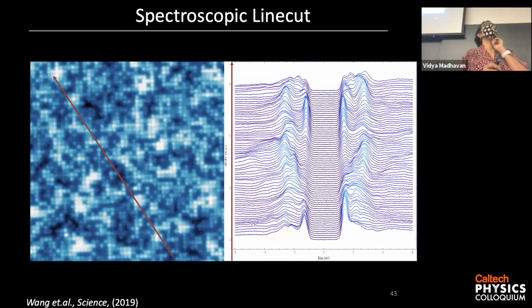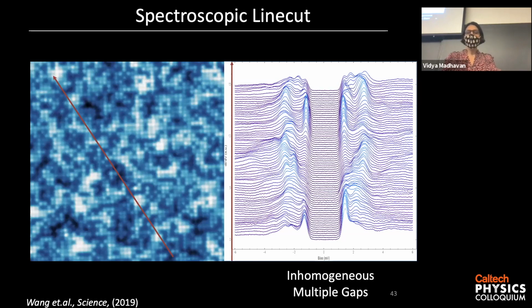And now at low temperatures, you can ask whether this material is superconducting. So here at this point, you can take a spectrum. And as I promised, the spectrum looks exactly like you thought it would. You see this sharp coherence peak at the gap edge, and then basically the density of states drops to 0. So this is literally 0 density of states inside the gap. One interesting thing is that you don't have just one coherence peak, you have many. In fact, sometimes you have even 3 coherence peaks at the same point. That is because those different pockets that I showed you have different gap magnitudes.